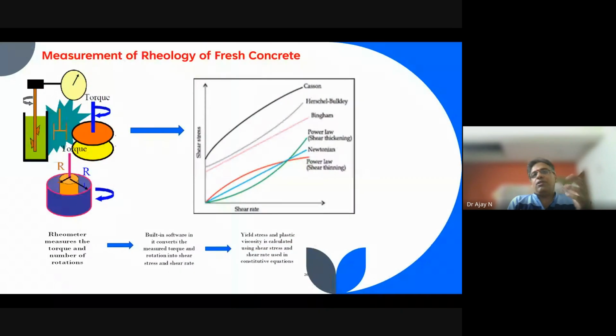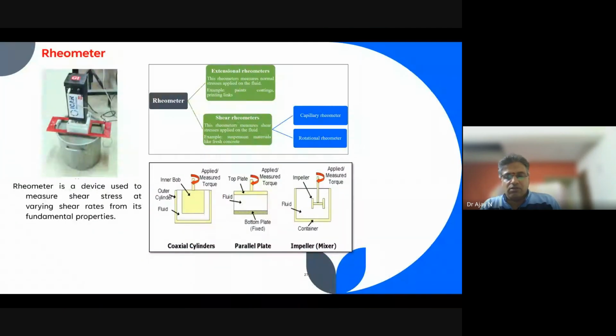So how will you measure rheology? We have to measure the torque as well as the rotations, and this torque and rotation we have to fit with mathematical models. They were developed by Newton, Herschel-Bulkley, Bingham, and power law, that is shear thinning and thickening. These are the mathematical models. So these values have to be fitted to those mathematical models. And among these equations, the Bingham equation is the best fit for concrete in the fresh condition, because we are measuring this